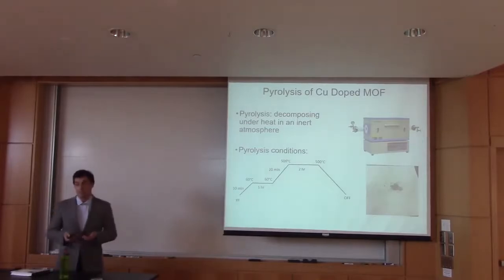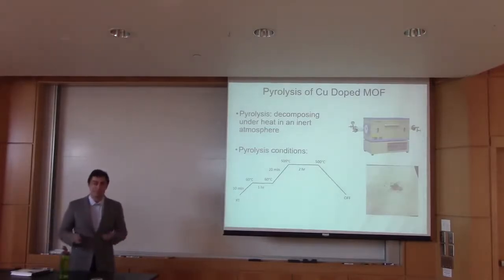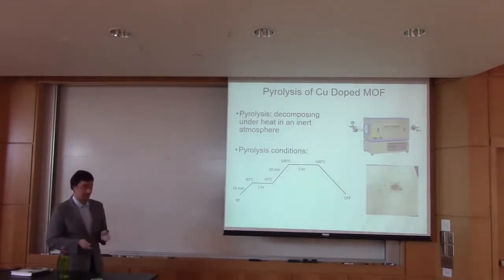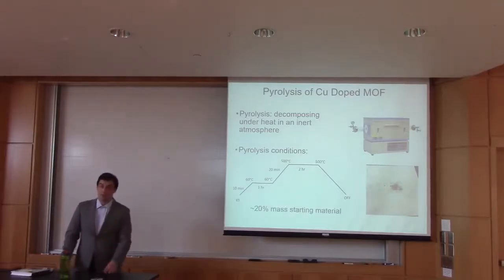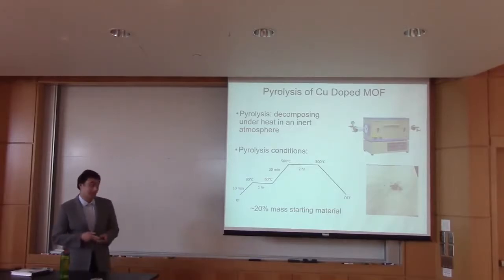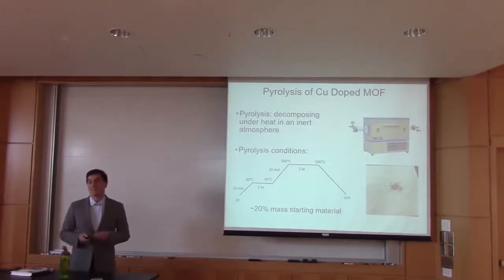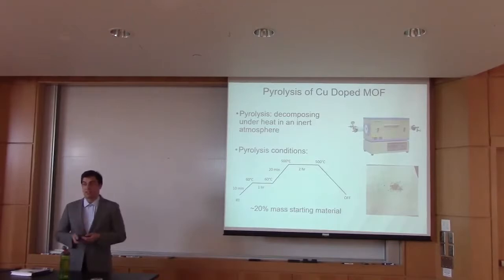We see what looks like a burnt powder because it's basically a burnt powder. We have this black-gray powder. We burnt off all of the organic units and have just been left with those metal oxides and our active catalyst. We have about 20% mass of our starting material, which is expected as we're burning off those organic units and losing a lot of that mass. This is another reason we needed to fix that earlier yield step. Otherwise, I had to repeat this many times until we fixed it, and scaling it wasn't really feasible.